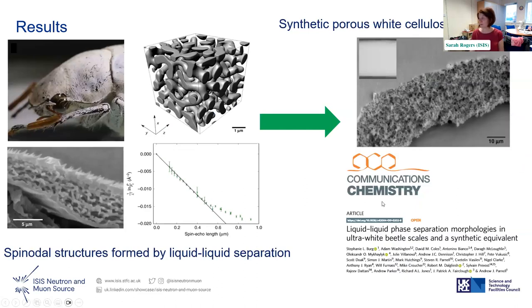And so what they've managed to do is that they've worked out from combining all these different measurements what the structures are. So it's these spinodal type structures. And then actually how they were formed was by liquid-liquid separation. So they tracked that with the spin echo SANS. And so now they've been able to make a synthetic porous white cellulose acetate film, which looks like the beetle's shell. And so they can now hopefully make white structural color paint.